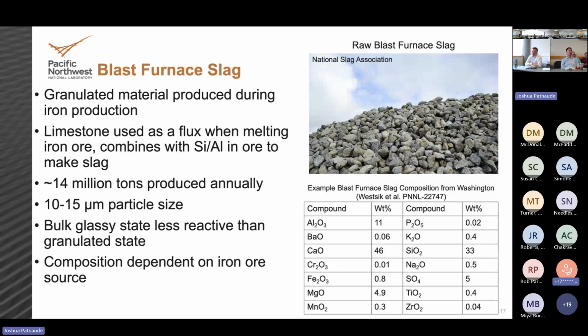The next big one for us is blast furnace slag, which is a byproduct of iron production. So again, we take iron ore, you put it into a high temperature process. You're trying to separate the iron from everything in the ore that it's carrying it. And the resulting material that comes at the back end looks a lot like a glass. And you combine the limestone that's used as a flux in the processing. And what you get is slag, blast furnace slag. Again, material that contains calcium, aluminum, silicon, comes out of a high temperature process.